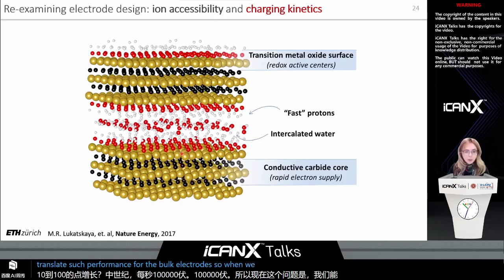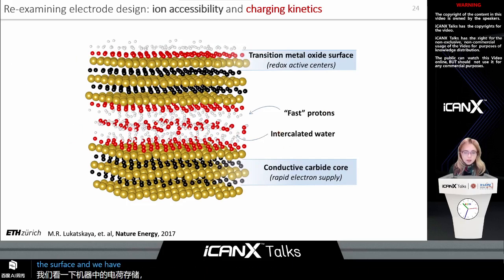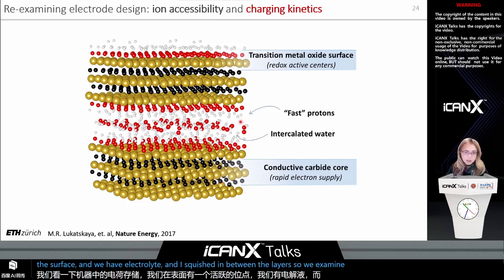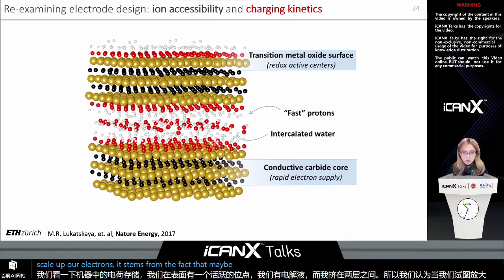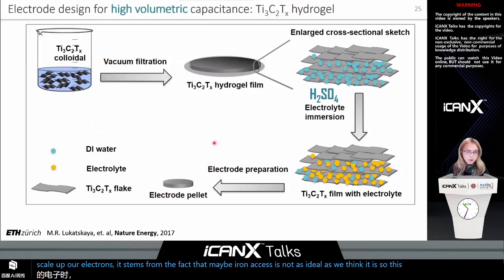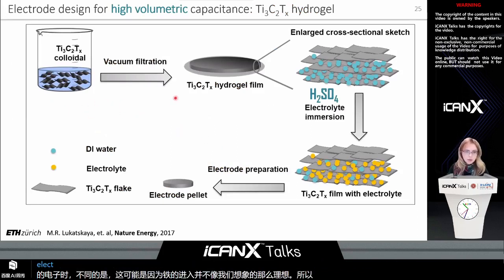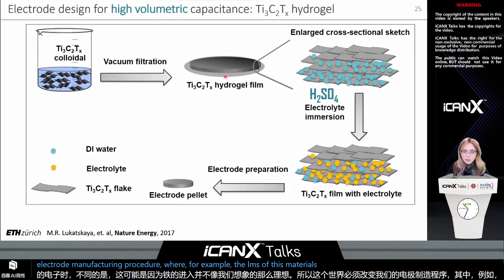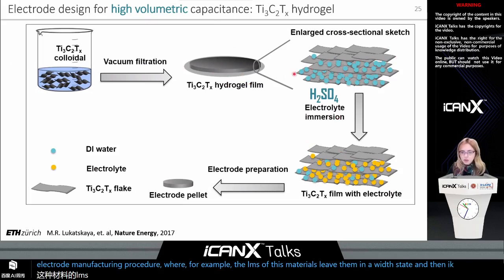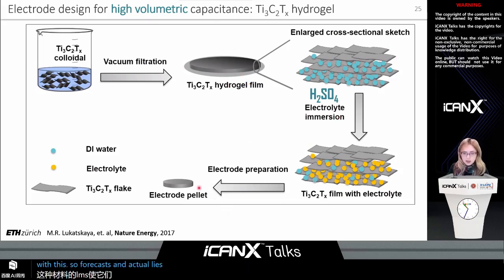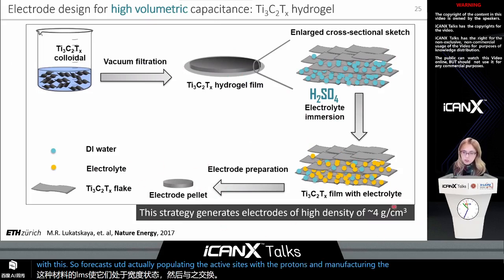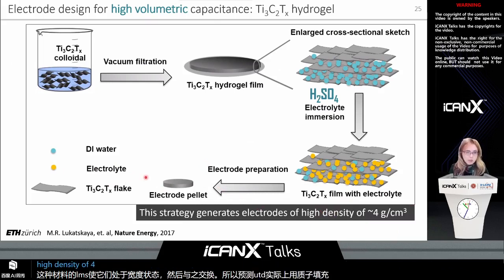So when we look at the charge storage in MXenes, we have these active sites at the surface, and we have electrolyte and ions squished in between the layers. So we re-examined and thought that the difference when we try to scale up our electrodes stems from the fact that maybe ion access is not as ideal as we think it is. So this brought us to changing our electrode manufacturing procedure, where, for example, we make films of these materials, leave them in a wet state, and then exchange it with the sulfuric acid electrolyte, pre-populating the active sites with the protons, and manufacturing the electrode, which still maintains high density of 4 grams per cubic centimeter.